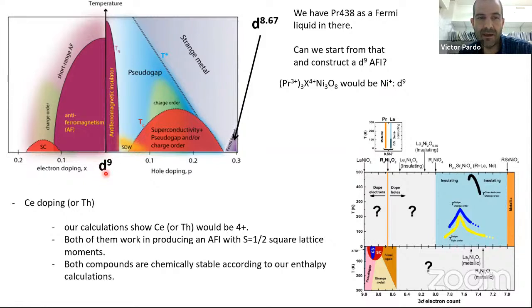And the idea would be, okay, if you do that, do you get an antiferromagnetic insulator like it happens in the cuprates? If the answer is yes, then you would have, well, at least from this, you know it from experiments, and this end you would know it from calculations. You would be in a good position to at least mimic 2 of the points of the phase diagram of the cuprates. And if you dope it slightly, maybe you can reach superconductivity.